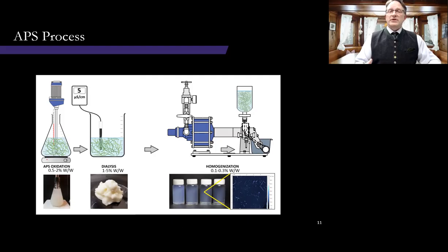Once the reaction goes to completion and we quench it, it requires a purification step, and we do that through dialysis. And here, dialysis takes about 3 to 4 days. We try to get it down to a fairly low conductivity. And the finished product looks like this. It's about 1 to 5 weight percent fibers, still fibrous, which requires a third step of mechanical defiberization.